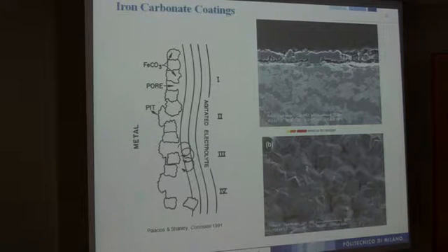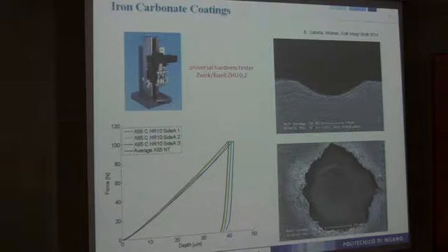What is known is that usually these products form compact layers on the surface of the steel with a high protective characteristic. Nevertheless, it is also known that due to some accidental action, you might have detaching of this coating from the substrate, and then the fluid flow can remove some particles of this scale, and this produces a very localized dangerous corrosion.